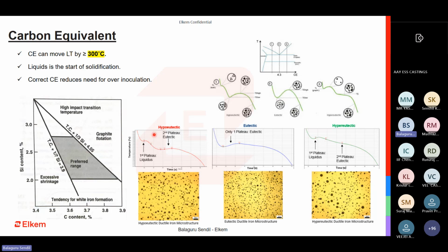If you look at the microstructure, when you're having hypo, the image kind of looks like this. The eutectic is something very ideal. We have very small, uniform-size nodules distributed. When it comes to hyper, you see slightly bigger nodules, primary graphites, because here the primary graphite comes out first.